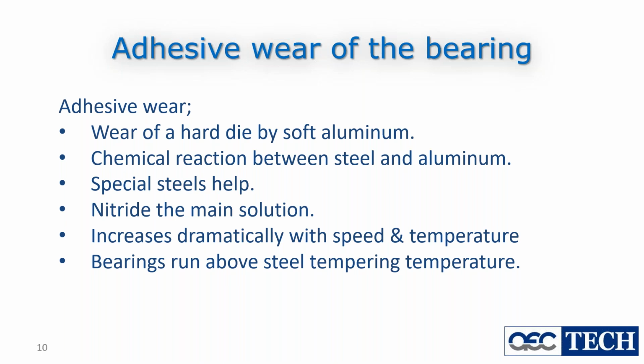So soft aluminum can wear the hard die because the chemical reaction or solubility of aluminum in iron can affect that. So special steels can help. Special materials like H13 or hot work tool steel can retain the hardness up to 600 degrees C. And nitriding the surface will improve it to a good extent, maybe 3 times or up to 6 times better in wear life. And also speed and temperature. Aluminum alloy is also effective, but increasing the speed and temperature dramatically will increase the wear.